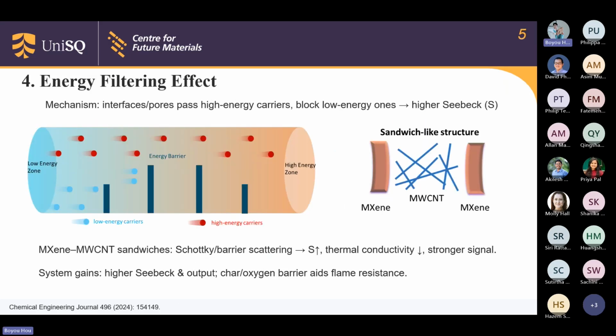And the second mechanism is energy filtering. Energy filtering is like using a sieve. We add gentle barriers so that high-energy charge carriers contribute more than low-energy ones. When we do this, the Seebeck coefficient goes up, so we get more voltage per degree of temperature difference while keeping enough conductivity, so current can still flow.